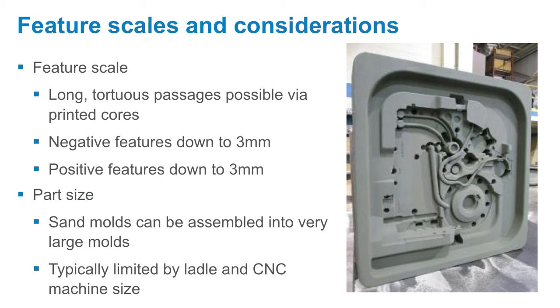One of the most exciting things, though, is that these sand molds are basically like giant Legos. It's only 13 cents a cubic inch, so you can estimate the cost pretty quickly. But you can design these mold components with as many alignment features as is necessary to tile them together to make very large sand molds. So at that point, the only limiting factor in how big the parts are that you can make is how big a ladle, how big a pot of molten metal you have.